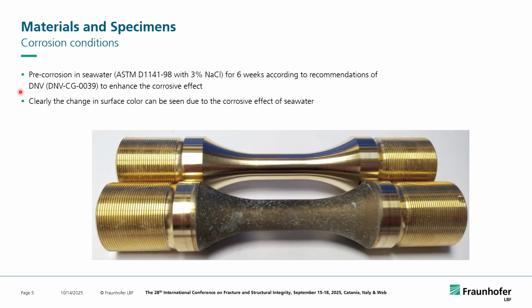Before we went on with the pure testing, the fatigue testing under seawater, we made some pre-corrosion in artificial seawater. Artificial seawater is used according to the ASTM standard provided here with 3% sodium chloride. And we kept it there for 6 weeks in accordance to DNV. So the DNV as a certification body was involved in the research project, and together with them we agreed to make a pre-corrosion of the material.